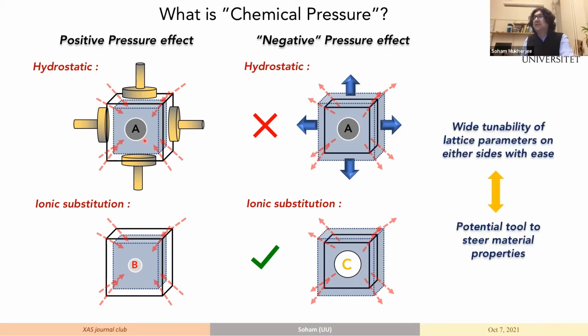And not only that, the tunability, of course, on both sides is enormous, because you are now creating an internal pressure effect within the system by changing the size of the ion. And it has been used ever since as a potential tool to change material properties, because you can do alloy doping as well, for example, and then immediately alter the electronic landscape. So we wanted to check this concept again in terms of the local structures.